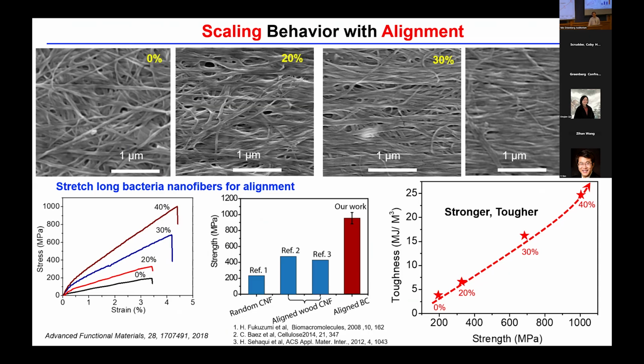Because that's the number that you can get funded. So we propose a number and then we push the student to come up with ideas. In this case, we have a random fiber network and we have to align it. If you work on carbon nanotubes, you have to work with alignment to maximize the fiber-fiber interaction. You can maximize the contact, so the secondary bond. So we take these long bacterial fibers, we soak them, we stretch them, and we can get to 1 gigapascal, right? So good. Then we proved to the Air Force we can make 1 gigapascal. Then the question is, how do we make a lot, to make a structure for the Air Force, right?